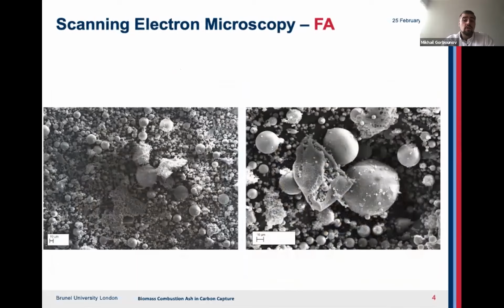The surface morphology of the raw fly ash has been evaluated using the scanning electron microscopy, or SEM. As can be inferred from the slide, the fly ash consists of a mixture of spherical particulates with widely varying size, agglomerations of these particles, and some porous matter as well. The spherical particles are typical for fly ashes and can be attributed to their amorphous coating formed as a result of relatively abrupt post-combustion. As clearly demonstrated on the image on the right, though, there are stark differences in the various particles present in the fly ash, as well as the presence of some porosity.